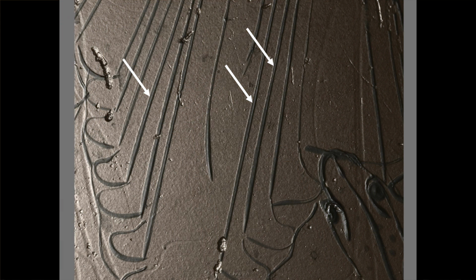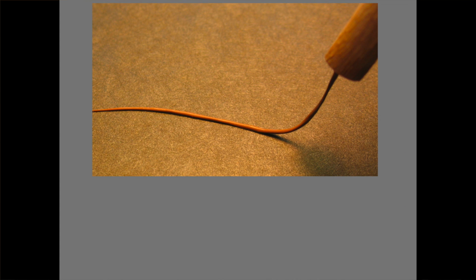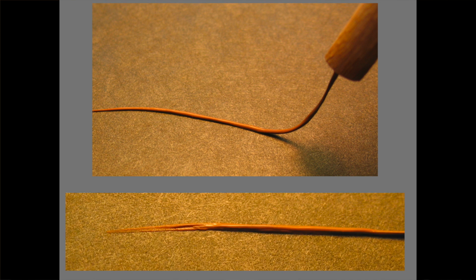We found that this technique only produces lines with ridges and not the second line type that we had observed, the lines characterized by a furrow running through the middle. We were, however, able to replicate these lines by setting down the tip of our brush, as you can see here, and pulling it across the surface. The action of the brush hair as it is pulled through the clay body across the surface produces the characteristic furrow. Unlike the laid lines, these lines can be longer than the length of the brush hair. We gave this line type the name pulled relief line or simply pulled line.